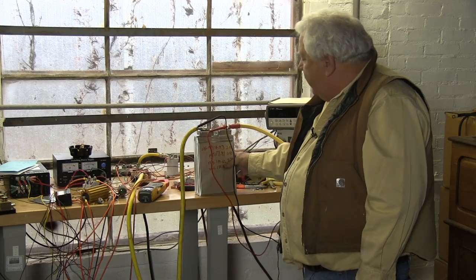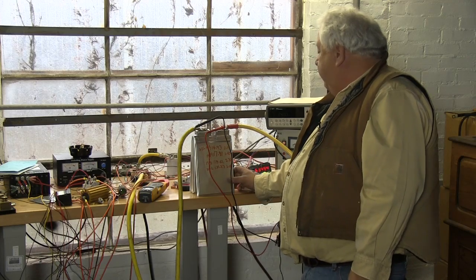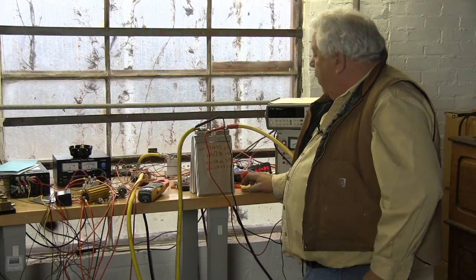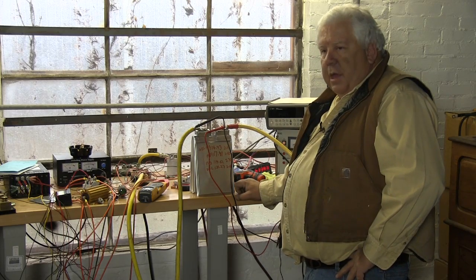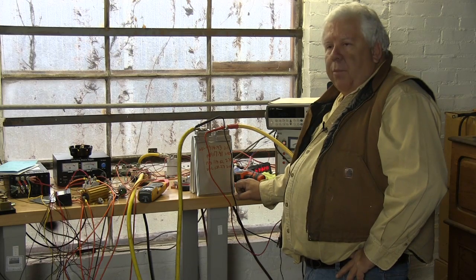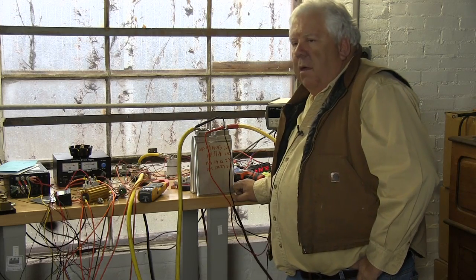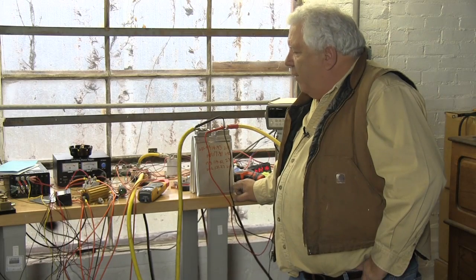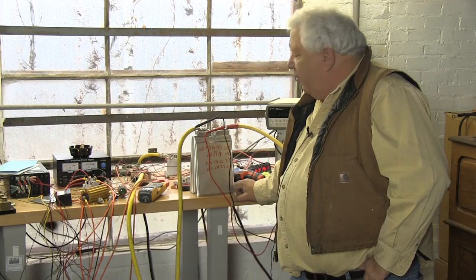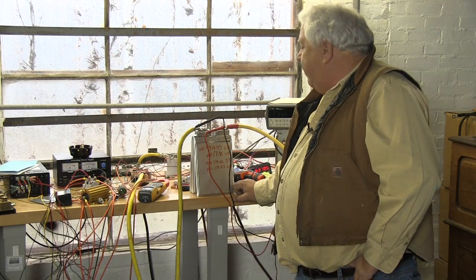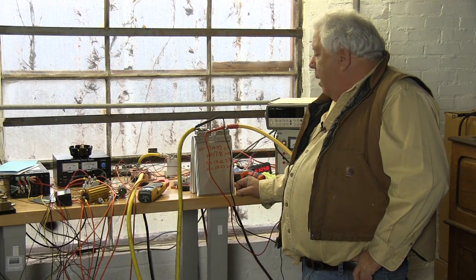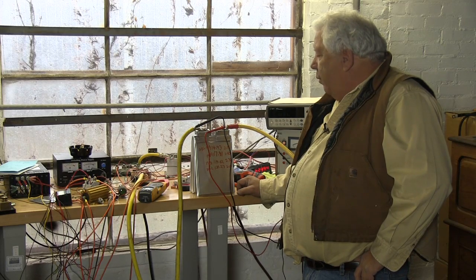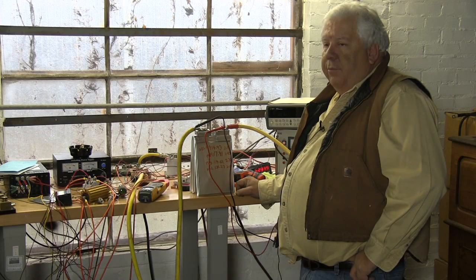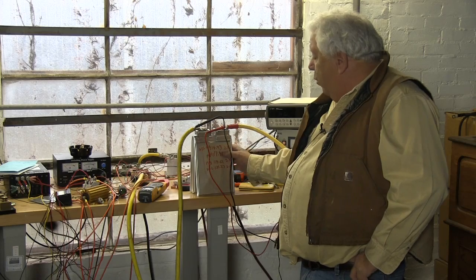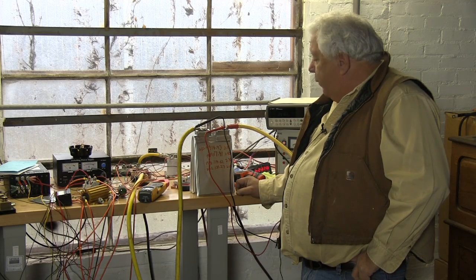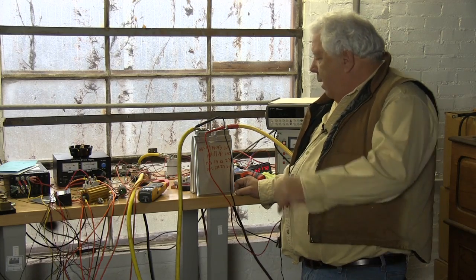cell here. The next step, we're going to try our resin casting again, only this time in a 1 cell version, and then measure the discharge and recharge and see if that may be our problem. If it is, then our basic assembly of the module into 40 volts and our 12S 4P would still be manageable, but we can't cast it in resin. If this casts in resin and retains its capacity, then I'm going to say that I don't really want to fool with these cells in groups of 48 because it's just too expensive for the failures. We'll have to monitor the cells individually and treat them more like our regular prismatic cell.